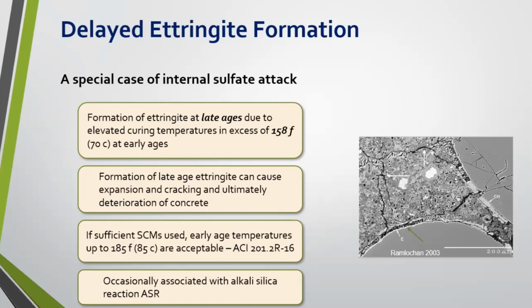So just an honorable mention here when it comes to delayed ettringite formation. If sufficient SCMs are used, and the right SCMs, early age temperatures up to 185 degrees Fahrenheit are acceptable according to ACI 201.2. And so we'll get into this in a minute as we talk about slag cement, but there are some ways to combat that delayed ettringite formation.